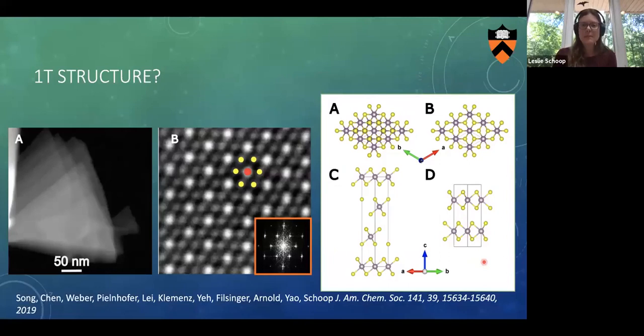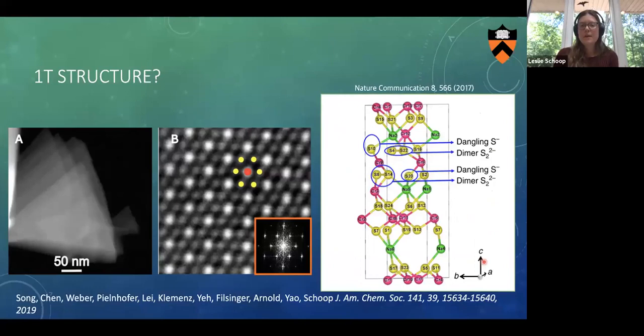And Xiaoyu was very careful and she found this paper, which really saved us, where people put sodium chromium disulfide in a battery and they electrochemically pulled out the sodium. And what they found is once they take out some sodium, the chromium migrates into the sodium space. So instead of making beautiful, nice layered chromium disulfide, what they did make was a three-dimensional bonded solid.